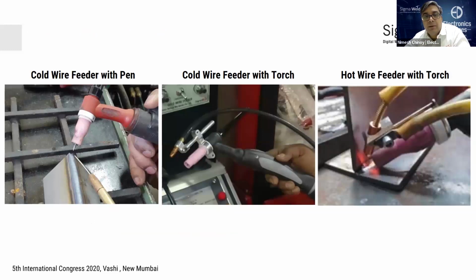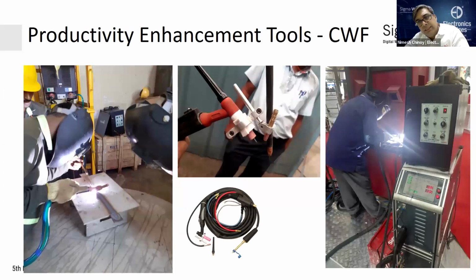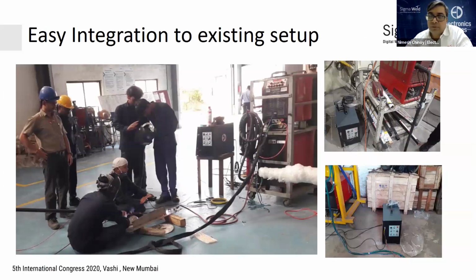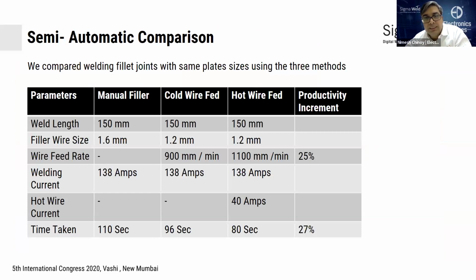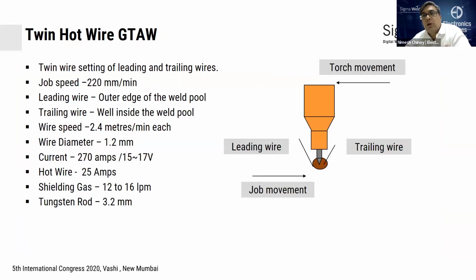You can use it with a pen right mounted onto the torch itself, or hot wire as shown on the third figure. This is easy to retrofit on your existing setup. So it helps you use your existing setup of TIG welding machines. You need not invest in newer setup. It can be integrated with any old equipments, whether it's a European or an Indian or an old machine, it can do the works. Here you can see the productivity improvement is close to 25% and time taken is reduced by about 27%. You can also use twin wire, but this is usually used in automated setups.